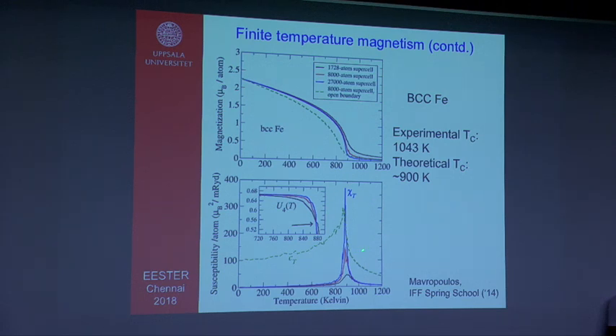But the other thing I was talking about is actually looking into the cumulant crossing method, fourth order cumulant crossing method, as a function of temperature. So these are actually calculated here, three different curves for three different system sizes, and when they cross each other, that is the point where the critical temperature should be. Also, you can look into the susceptibility. It has a peak at the phase transition. Specific heat, it has a peak at the phase transition. So by several different means, you can find out the critical temperature for the system.